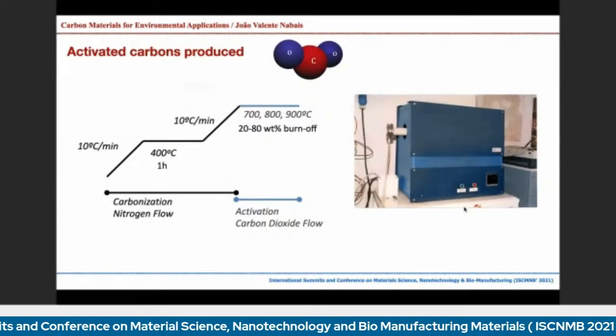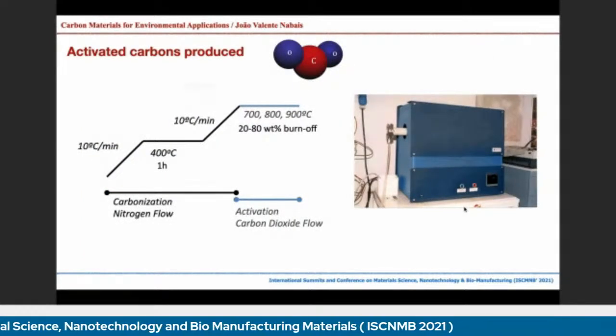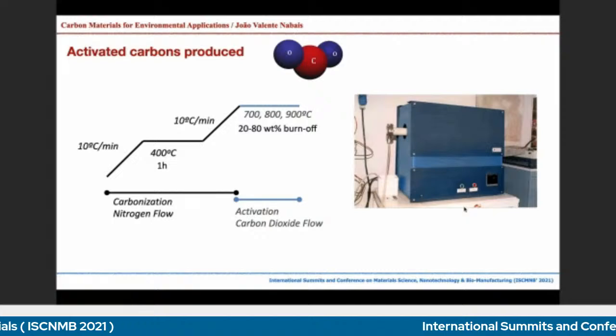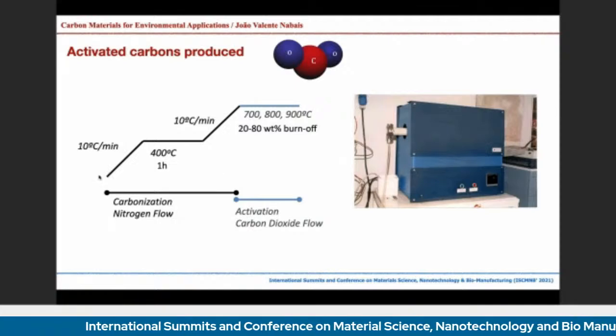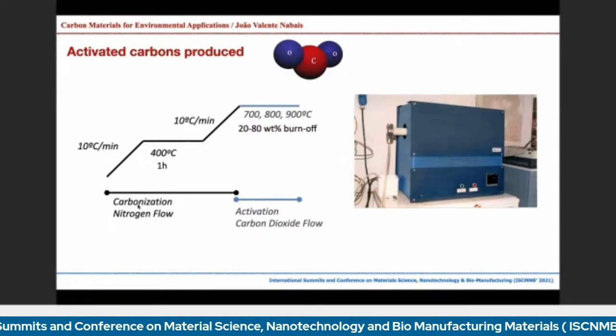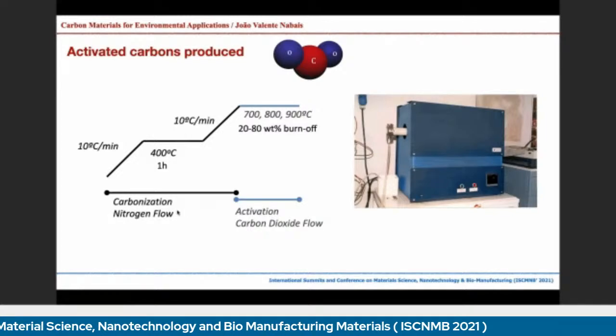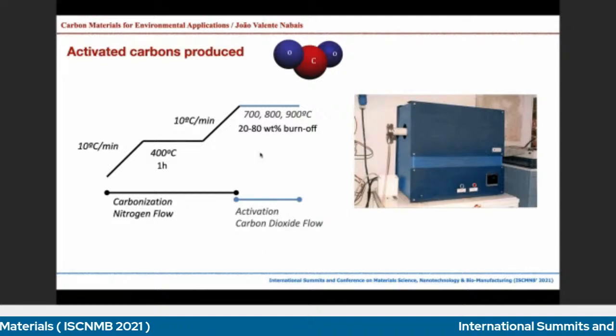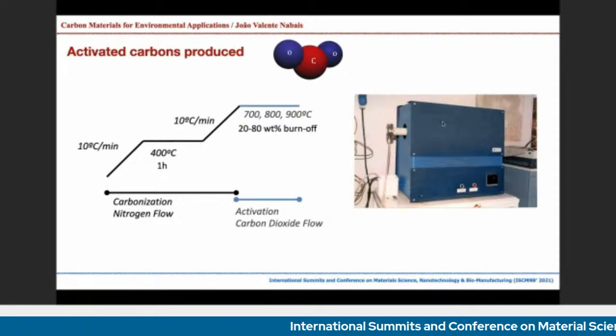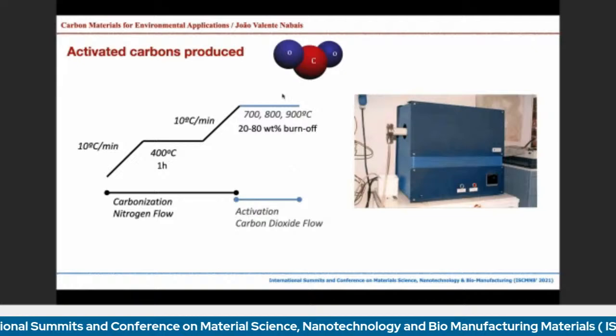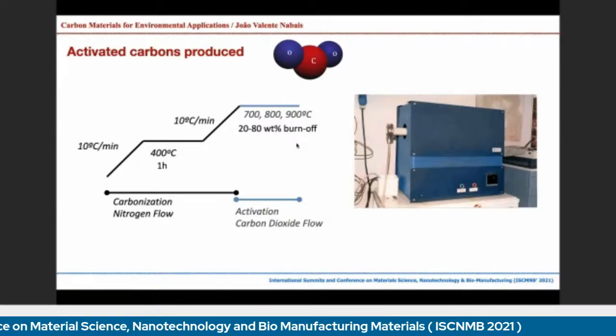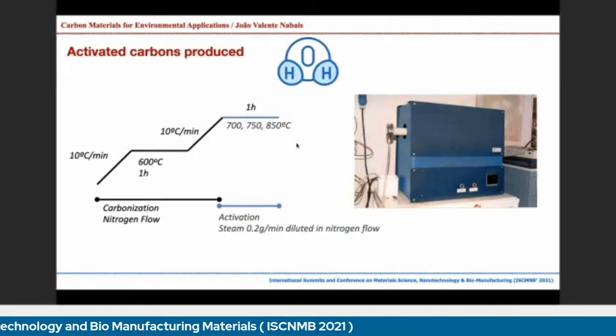Using these 5 different precursors, we have used 2 different methods for the production of activated carbons. First of all, with carbon dioxide. So basically, we have used this horizontal furnace, with the heating process starting with the carbonization under a nitrogen flow, followed by an activation step with a carbon dioxide flow, which means that when the system reaches this temperature, we change the gas to the activating gas to promote activation of the materials. And then we have used as well water steam.